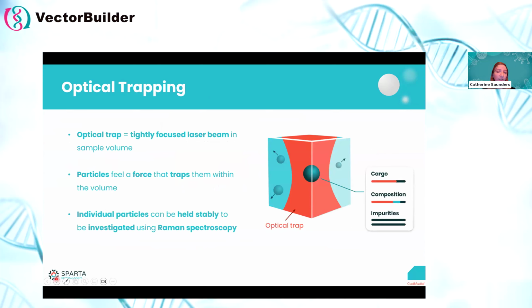So what we do is we then bring in our second Nobel Prize winning technique, which is optical trapping. In optical trapping, we take a very tightly focused laser beam and we shine this into a solution of the nanoparticles. This very tightly focused laser beam creates an optical trap or a confocal volume of less than half a femtoliter in the nanoparticle suspension. When nanoparticles diffuse into the volume, they feel a trapping force, and then they're stably held in this very small volume until we decide to release them.